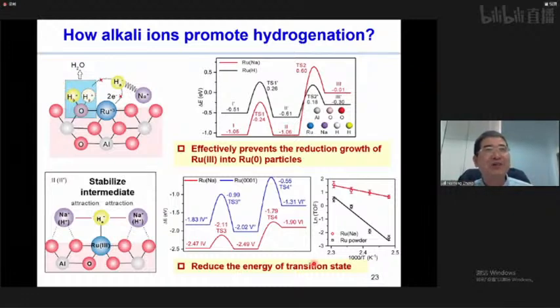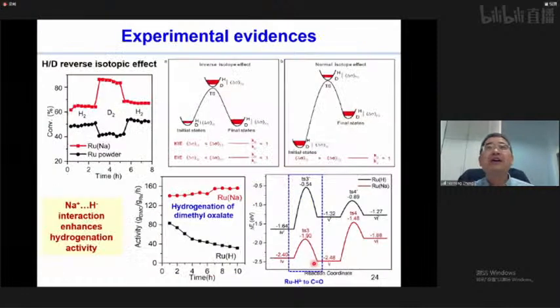Do we have any experimental evidence? The answer is yes. In most hydrogenation catalysis, if we replace the hydrogen by D2, by deuterium, because deuterium is heavier than hydrogen, normally we see a decrease in activity. But in this case, we found that actually the use of deuterium can enhance the activity. It's mainly because we reduce the energy barriers of the reaction. So indeed, we have the evidence for our proposals.